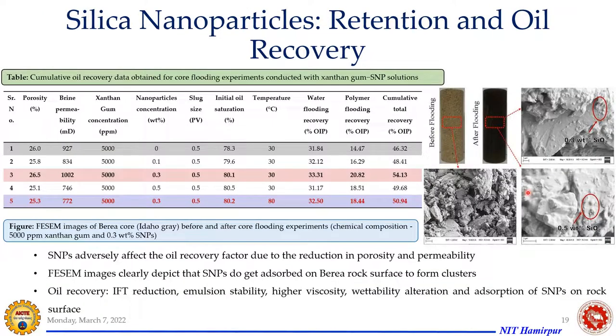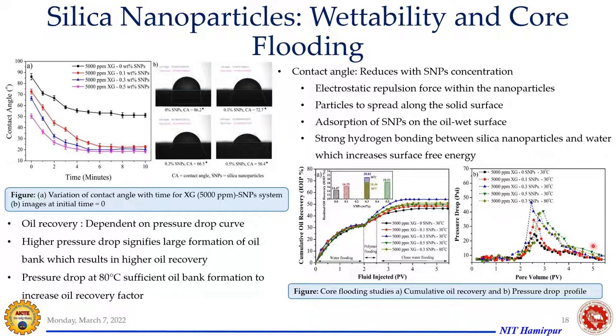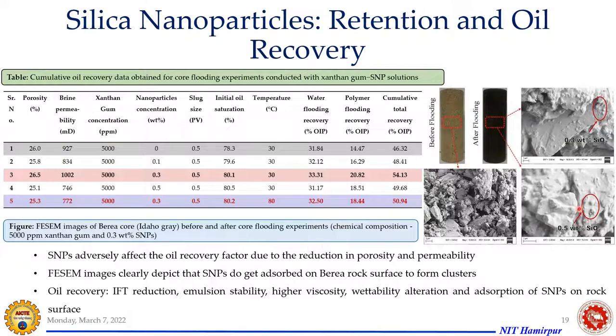And as I was talking about, this other way of detecting the pore blockage is the FESEM image of your nanoparticle. So you can see here, this is the sample before the core flooding experiment, and this is the sample that we received after the core flooding experiment. This is the image before core flooding, and when we did this flooding, because of this pressure drop curve, which was saying there is some blockage happening inside the pores, we can identify it in the FESEM image. You can see there are nanoparticles which are getting agglomerated, and these are kind of blocking the pores. There is some pore blockage. This is what we have confirmed from this FESEM image.